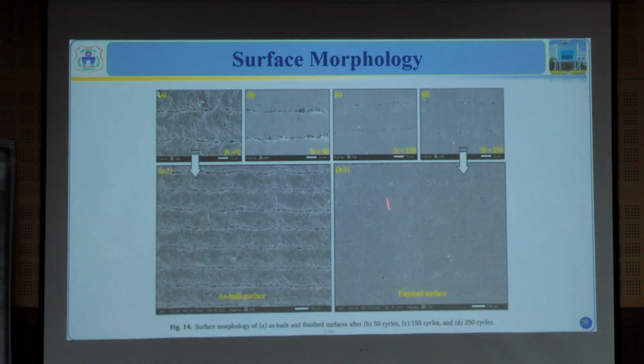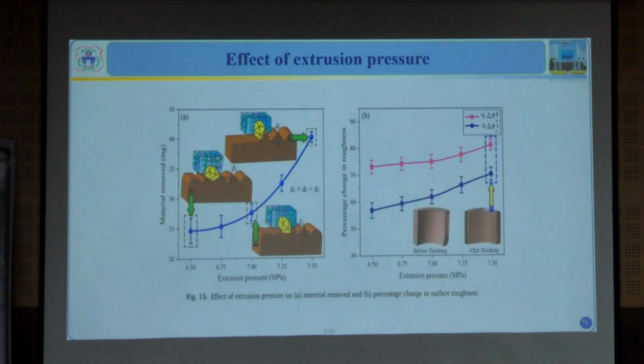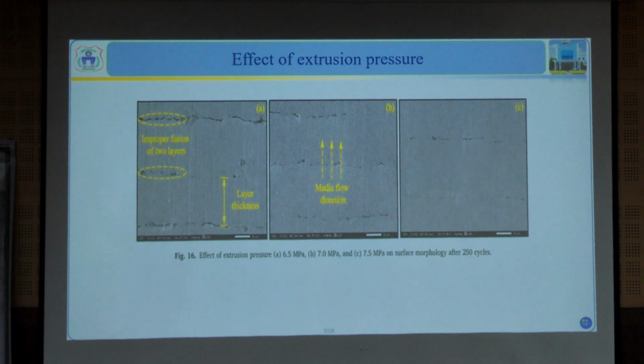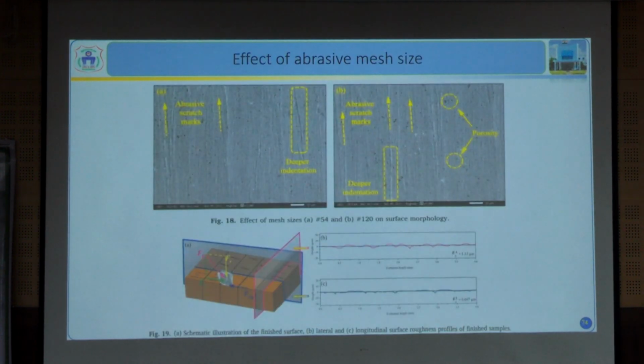You can also see the surface morphology with respect to different cycles like 50 cycles, 150 and 250 cycles, and how the final finished surface looks, and how the surface looks before, as a 3D printed component and then as a finished component. The effect of every parameter is discussed, to know the media flow direction and also to observe the layer thickness, mainly targeting the as-built component and the finished component.